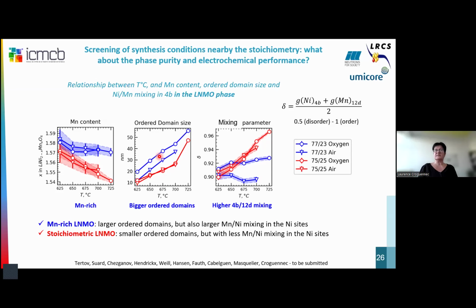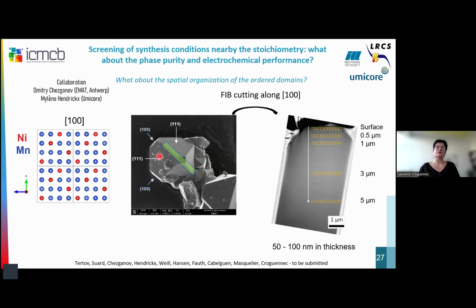So, of course, it's interesting to determine how these domains are organized. And for that, we did some microscopy because, as you have seen, these materials are those that behave better in the battery. So it's interesting to understand how this ordered domain is organized and to propose a hypothesis for why it gives better electrochemistry. As mentioned just before, these crystallographic planes allow us to see the arrangement between the nickel and the manganese, and thus to have a highlight about the extent of the ordering or defects in these materials.